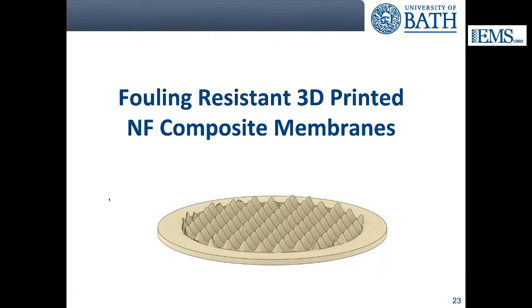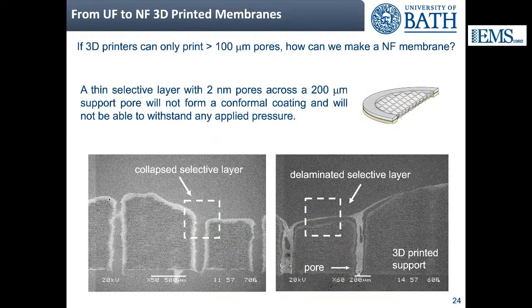Let me come now to more recent work we've done on 3D printed nanofiltration membranes. When we started doing this, we had a practical problem. Your 3D printer has resolution limits. And so you have these large pores in a 3D printer, but then you have this very thin selective layer, for example, PVDF, which has 2 nanometer pores, is only a few micrometers thick, and it should bridge the gap between this huge pore in the 3D printed support. And fundamentally, it didn't work.